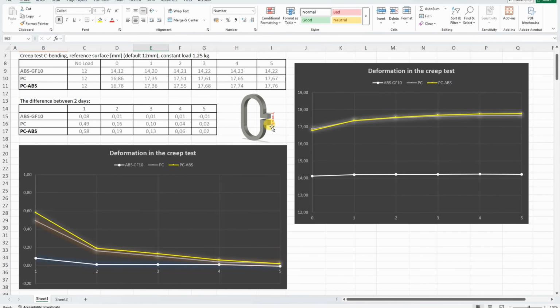On this graph we can see the distance between the reference surfaces, and we can see more deformation on PC and PC ABS, very minimal deformation on ABS-GF. But the creeping is the difference between 2 days, and that's presented on the second graph. And we can see very similar creeping of the PC and PC ABS, and extremely minimal on ABS-GF. Basically, it stopped with deformation after day 2.